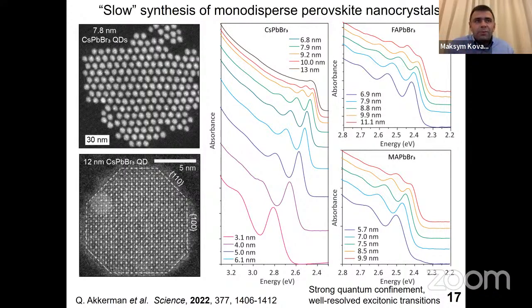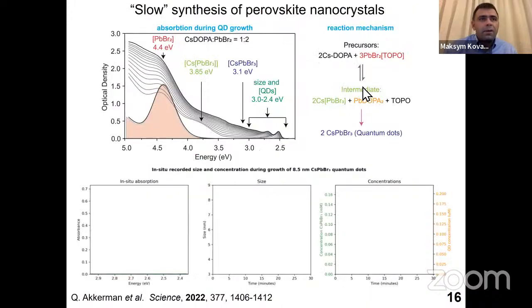And the reason here is exactly what we discussed before: you no longer use amines in the synthesis. So this mechanism of 100 lattice plane stabilization doesn't hold anymore. You don't have any ligand which binds very strongly in this system, which is a blessing and a curse. It's a blessing because you can use such a synthesis as a first step to functionalize your nanocrystals with any ligand that we want. You can put on any molecule that will have high affinity to the surface, because in the synthesis you don't have any such molecule. So you can decouple the formation of nanocrystals from their subsequent surface functionalization.